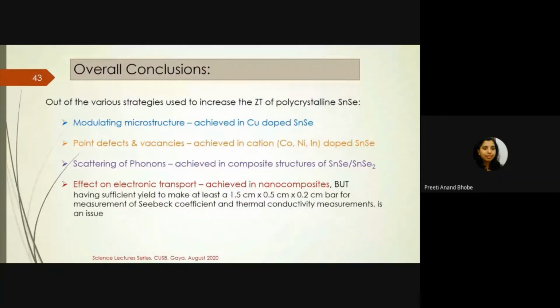To improve the ZT, the methods that we tried out were we tried to put in copper in SnSe and we got a modulation in microstructure and it helped us improve the ZT. To check whether copper is the only substituent, we put copper, cobalt, nickel, indium, etc. in SnSe and we got point defects and vacancies and we reduced its thermal conductivity. Same way, when we made a composite of SnSe with SnSe two-phase, we found that we could scatter the phonons and hence bring down its thermal conductivity.